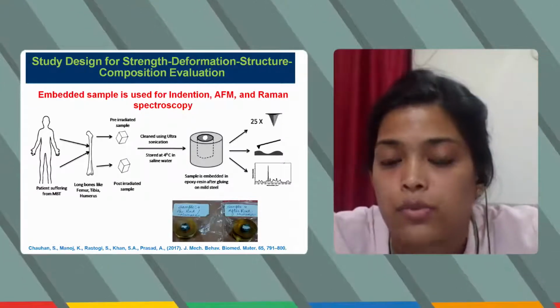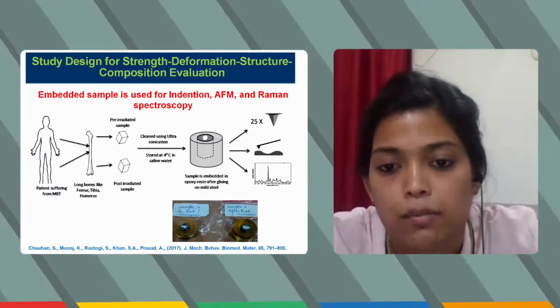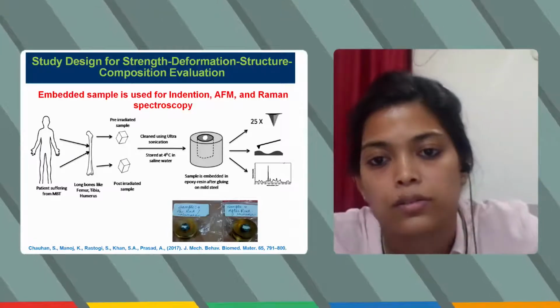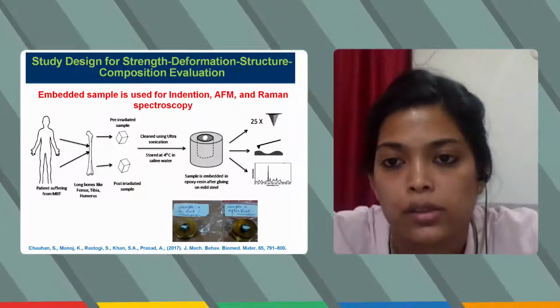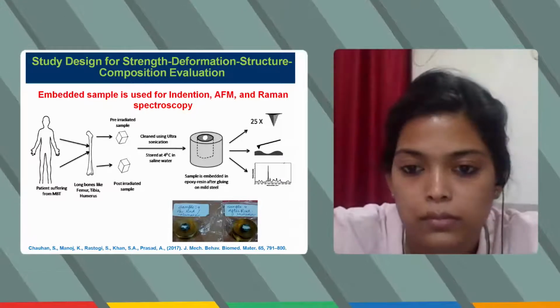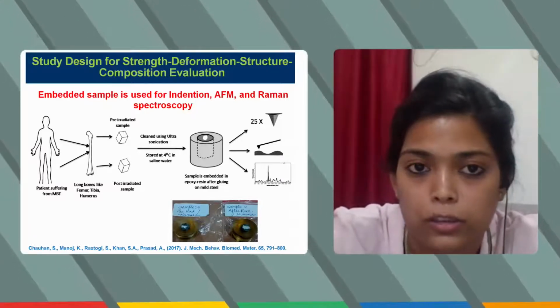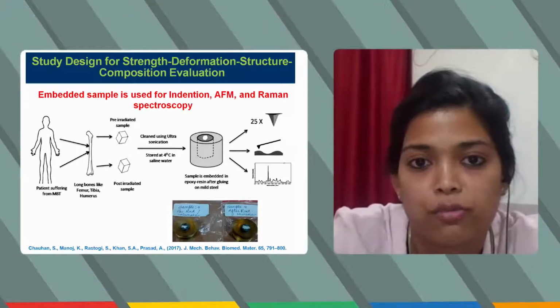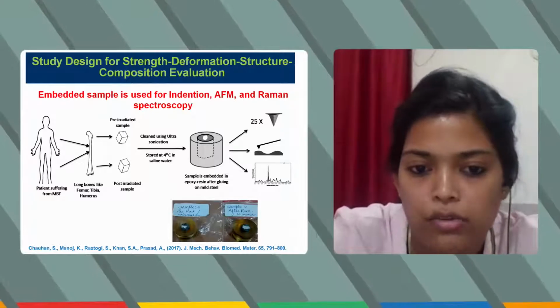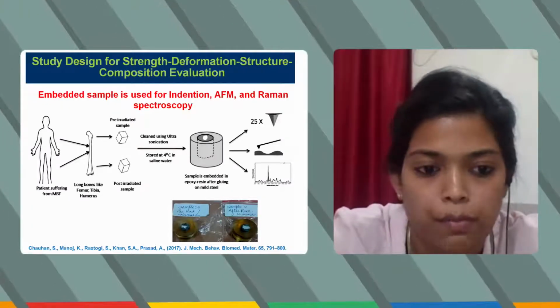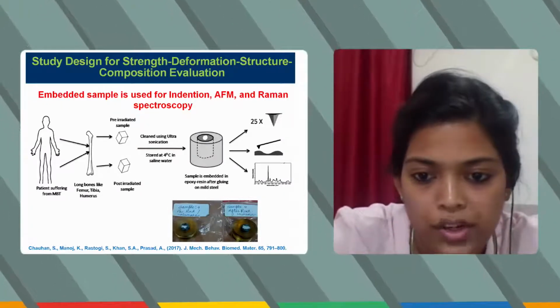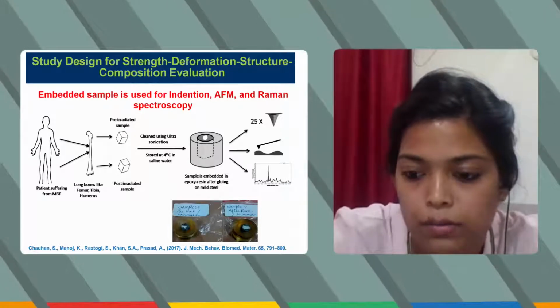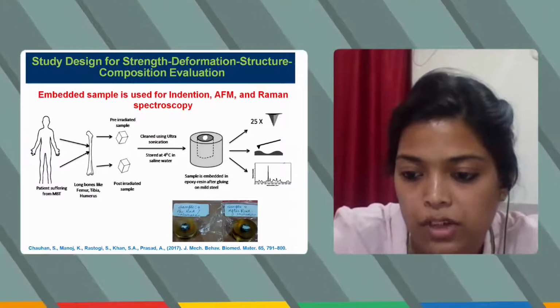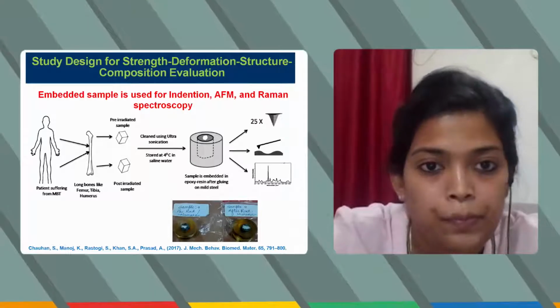And the sample is then processed so that testing can be done, by taking a cylinder of epoxy and then embedding the sample. And this sample is then placed for nano indentation, for AFM, for Raman spectroscopy. For micro CT, we have a different sample of the same patient. The study has already been published in the Journal of the Mechanical Behavior of Biomedical Materials.